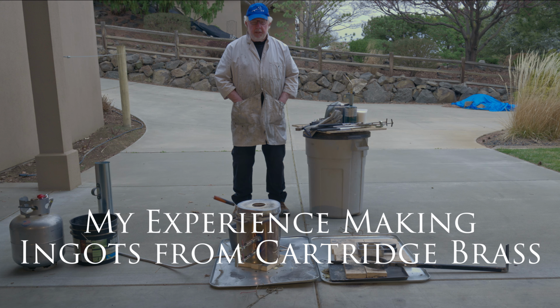For starting the furnace, a handy torch like this is good, but once it gets hot, you can shut it off, turn it on, shut it off, turn it on, and it's hot enough that the propane will just simply burn. This is graphite powder. In the bottom of the furnace, there is a small brick that the crucible sits on, and the crucible, when it gets hot, will stick to that brick. You need to put something in there as a release agent. Graphite powder works good for that. Or if you don't have any graphite powder, take a little square of cardboard and put it in the furnace and let it burn up underneath the crucible. It'll leave carbon products behind and the crucible won't stick.